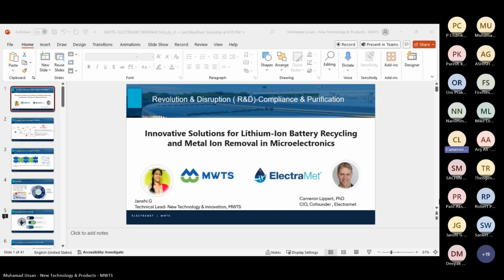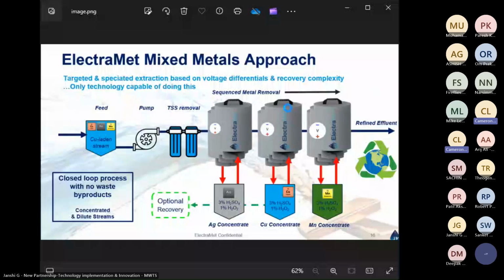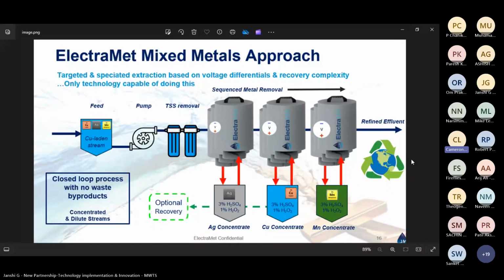Then the next one can do copper at a slightly higher voltage. Then we do things like cadmium, tin, lead at higher voltages. And then you start getting to this range where you're about the same voltage to make hydrogen gas, which is why it gets very finicky with nickel and cobalt. So you have to have very precise water chemistry and operational parameters to get the nickel and cobalt out at these higher voltages. Things like PGMs are going to be very, very low voltages, even lower than silver. The ones like manganese, that comes out in a different reactor design, but it's still pretty low voltages. So we can basically just on operational voltage, line these up and design these to target what metals you want. So it's just like dialing a knob on each one, setting 1, setting 2, setting 3. No process changes required.